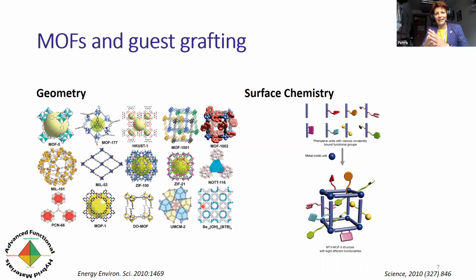So when I'm talking about geometry as one important thing, perhaps one of the unrivaled properties of metal organic frameworks is that we can have an absolutely huge number of possible pore sizes and shapes. And what's important to point out, when I mentioned how they're built up of these building blocks, is that the pores in the frameworks are part of the crystal structure. So they're very well determined in terms of shape and size, and they are the same throughout the crystal structure. So that is important. And of course, if we consider what they're made of, the inorganic node could typically be transition metal cations or metal oxide clusters, or the organic linkers can be polycarboxylates or heteroaromatic systems. So from inorganic and organic chemistry, we know that there are a lot of options for these.